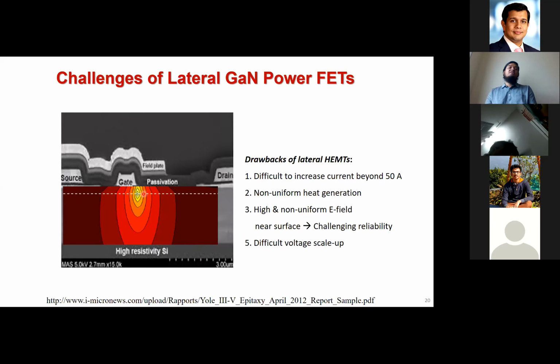The second biggest challenge is the electric field non-uniformity. Again, it's a surface device, and under high voltage conditions, there is a peak electric field at the surface that causes issues with device reliability. And the last point, which is pretty obvious: if you want to increase the blocking voltage of the device, the only way to do it is to increase the distance between gate and drain.